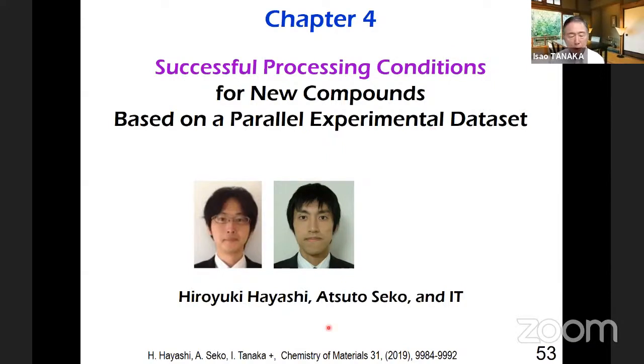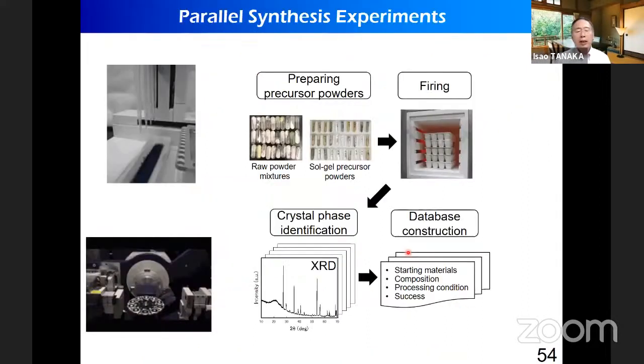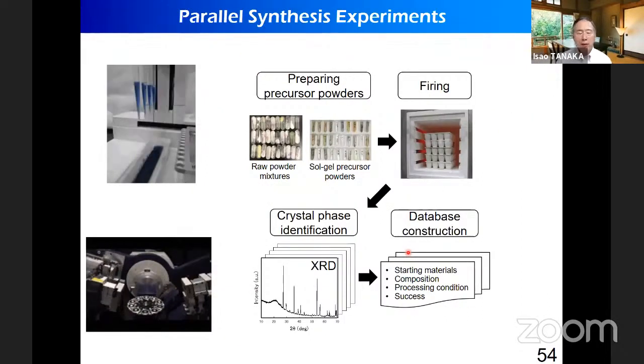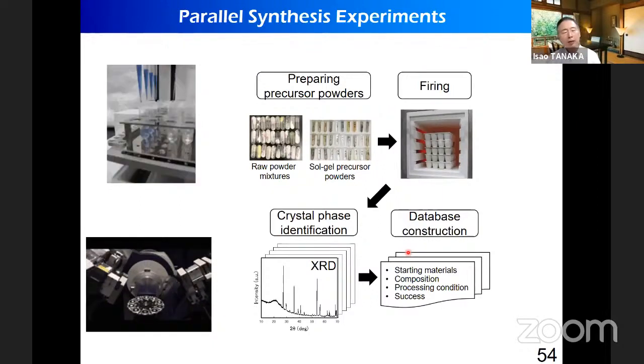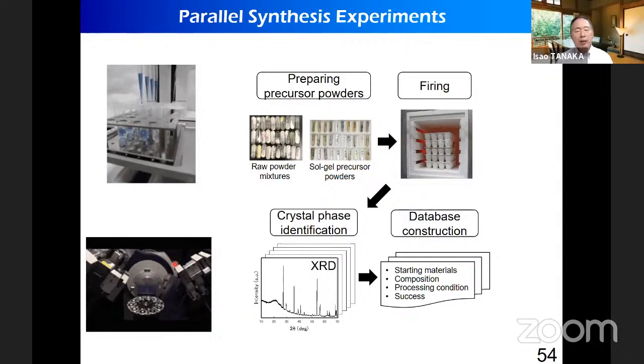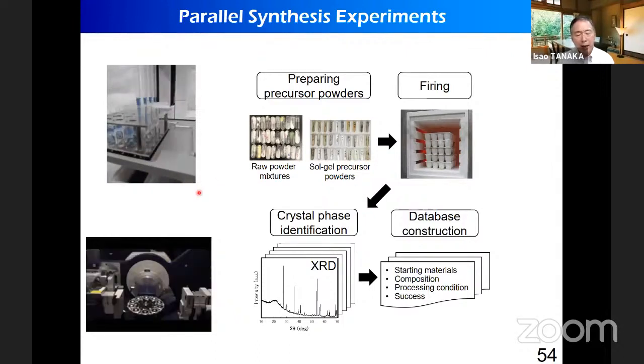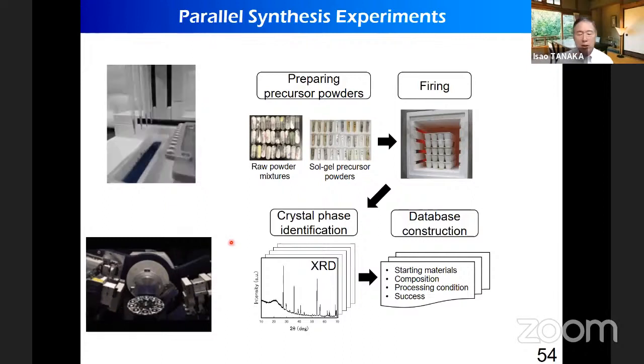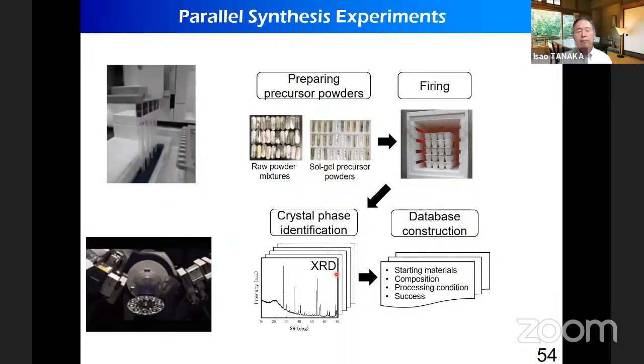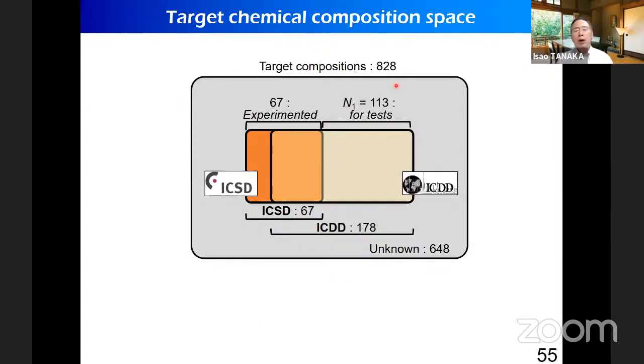This was done by those young people. In the lab, we are not doing only theoretical calculation, but we also have experimental capability. And we have established this type of parallel experiment together with parallel crystal structure identification by X-ray diffraction. As an example, we have pseudo-binary systems with a target composition of 828. Among them, 67 are registered in ICSD, and 178 are registered in ICDD.